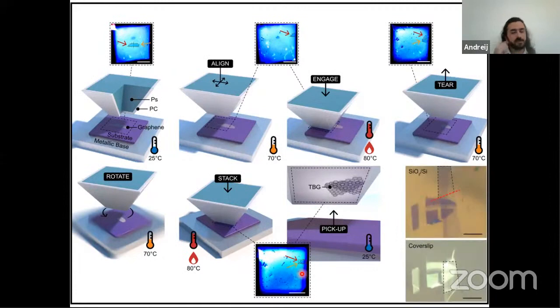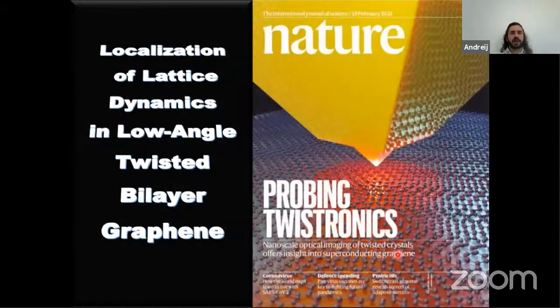We can transfer this TBG to every other substrate we desire. So, for example, we have here a graphene sample on top of a silicon dioxide silicon wafer. Then we make a cut here, pick this piece, rotate the base, this guy here, and we stack them, pick them, and transfer to a cover slip, which is another substrate. And here we have a twisted bilayer, clean, really good sample with no boron nitride flake on top of it. So we solved all the issues to get nice results, and I'll show our results from our paper, which is localization of lattice dynamics in low angle twisted bilayer graphene.